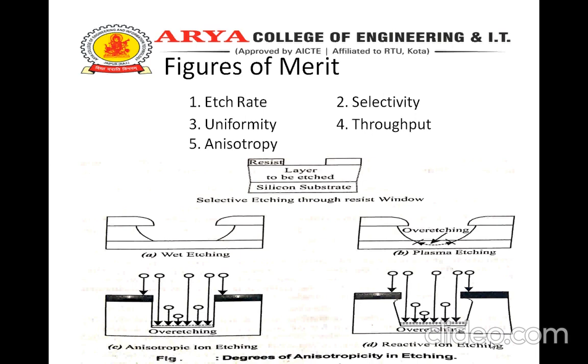...would also tend to etch the material laterally. As a result, the etched width would be different and larger than the designed dimension. In a plasma etching process, if the removal is primarily by physical bombardment — sputtering — the etching could be highly directional, determined by the direction of the electric field accelerating the bombarding ions. On the other hand, in a chemical process, the etching is generally isotropic. The sketch shows the result one expects with different degrees of anisotropy. With greater anisotropy, the fidelity relative to the mask dimension is greater. In isotropic etching, the result could show a degree of undercutting.